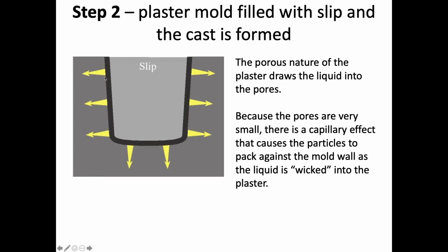So these arrows represent the liquid coming into the porous pores of the plaster, and leaving behind the particles. And the capillary force effect causes the particles to be packed onto the mold wall. So there's actually an effect that causes the particles to pack quite efficiently on the mold walls of this plaster mold.